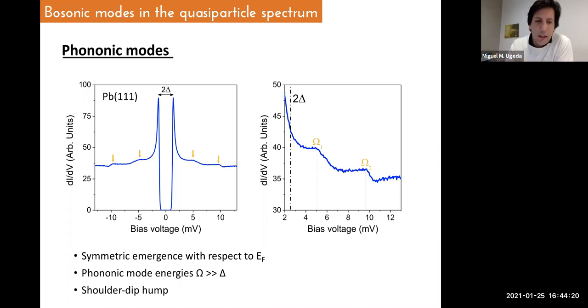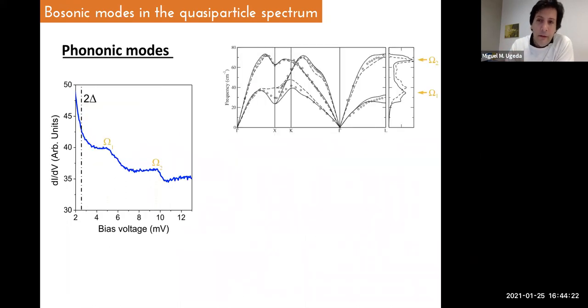So phononic modes actually follow in general positions in the density of states, the phononic dispersion. Here I show you the phononic dispersion for Pb(111). And this is multiplied by the Eliashberg function. So it gives in this range, I think this is around 10 millielectron volts translated into energy.